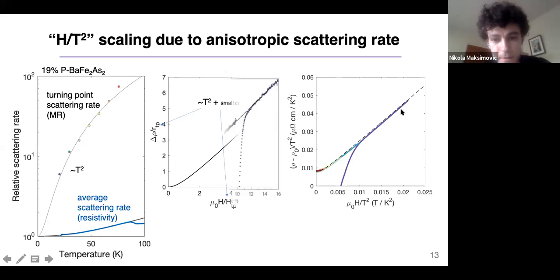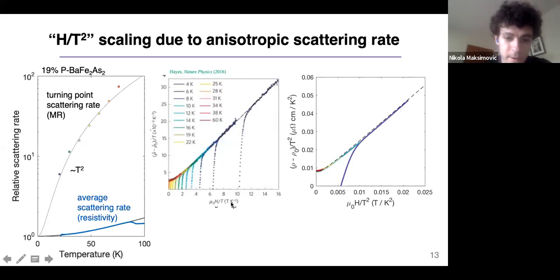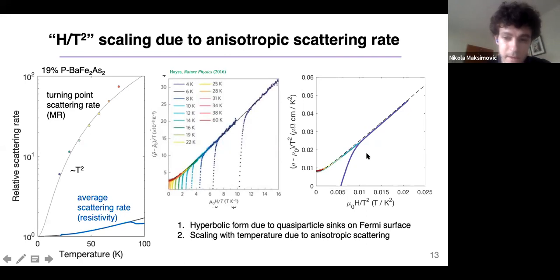This is reminiscent of what happens in the quantum critical samples, where you see the scaling with magnetic field divided by temperature and resistivity divided by temperature. Although in this case, given the model that we've applied, it seems to be the case that this kind of hyperbolic dependence on field arises due to these quasi-particle sinks on the Fermi surface. And the scaling with temperature may be due to a highly anisotropic scattering rate.